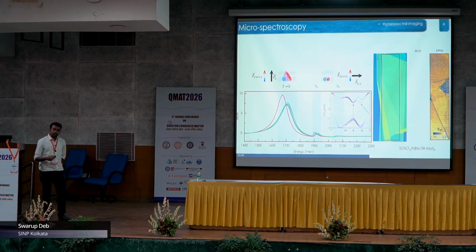And therefore, what we anticipated from classical electrostatics is that this exciton that has an out of plane dipole moment would be coupled to the out of plane ferroelectric field, simple P dot E. And the other exciton should not have any coupling to the electric field, because here E dot P is 0. Okay? So let's see how it goes.